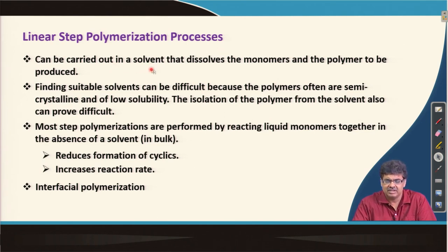It can be carried out in a solvent that dissolves the monomers or the polymers produced, but it is always difficult to find a solvent which can dissolve both polymers as well as the monomers, because polymers often are semi-crystalline and have low solubility. Also, after the reaction, the isolation of polymer from the solvent is a cumbersome, costly step.